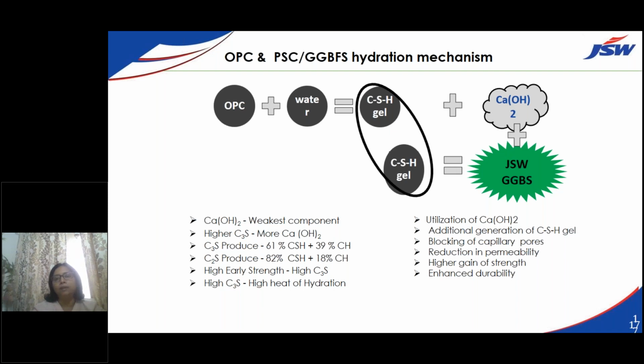So this calcium hydroxide, supposing a concrete which is having a lot of calcium hydroxide, you'll see white particles have come and the lime has leached out. What happens? Where lime has leached out, pores and voids will be formed, and through those pores and voids, the particles of the environmental agents are going to go inside. They are going to sit on the reinforcement rod or corrode the reinforcement rod, and there will be a lot of complication in the concrete structure. It will be distressed. So in order to finish this calcium hydroxide, what has happened?